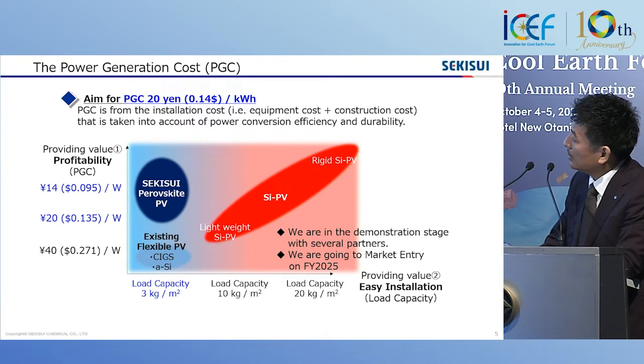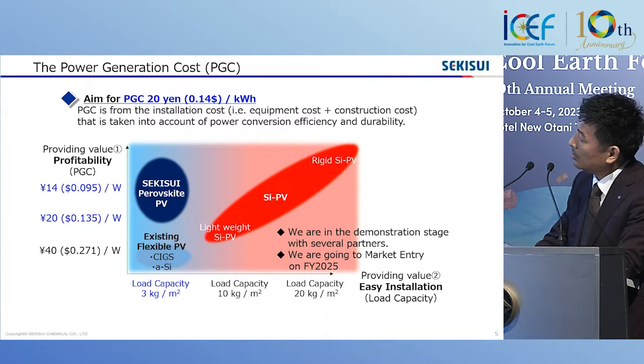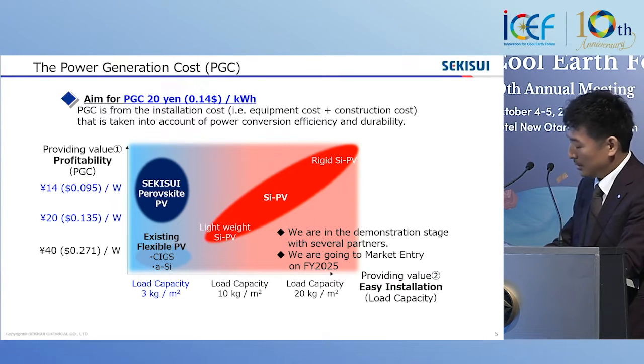We are also thinking about low load capacity. Normally a silicon solar cell shows a somewhat higher load capacity, like 20 kilograms per square meter or 10 kilograms per square meter, with very good efficiency and high durability. But our target is for perovskite solar cells to reach a very low load capacity, less than 3 kilograms per square meter, and low cost in the future.